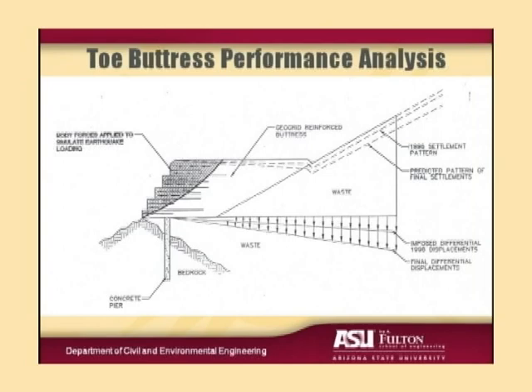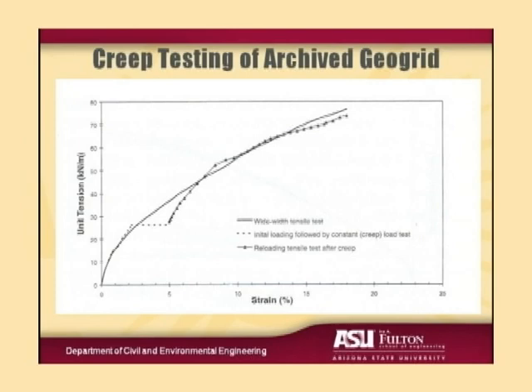And that resulted in tensile strains in the geogrid, which we then compared to the strength of the geogrid. But the question was, what strength should we use for the geogrid? It will have been undergoing creep for 30 years at that point, so what was a reliable strength to use? So we did some creep tests on geogrid, and this was the actual geogrid used in construction of the toe buttress. The geosynthetic companies, God bless them, they archive samples when they have a major project like this. So we were able to contact Tensar and get samples of the actual grid that was used in construction of the toe buttress. So we took those grid samples and we did about 4 or 5 of these tests.